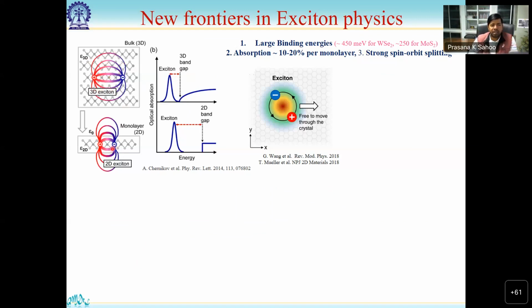But the moment you thin down to a single layer, because of the reduced dielectric screening, the electron and hole pair see more of the strong Coulomb interaction, and the binding energy can be stronger. They can be well-separated excitonic states well below the band gap of the 2D material. That is very interesting because compared to this semiconductor, excitonic transistors can be realized that have more secure transitions and more narrow emission, if we can harvest excitons.